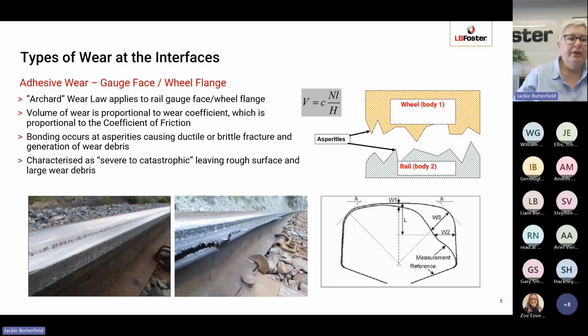So the bottom two pictures that you can see are a couple of examples of gauge face wear in heavy haul freight in North America. So you can see in the picture on the left that it is a very, very rough surface that's left behind. And in the picture on the right, again, you can see that there's a lot of damage to the gauge face of the rail, that pieces of the rail are actually coming away from the gauge face. But if you look at the rail foot, you can see the wear debris there. So you can see the silvery particles in the track bed and on the side of the rail. So this is adhesive wear.